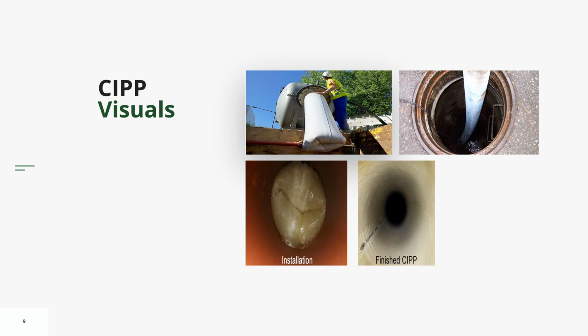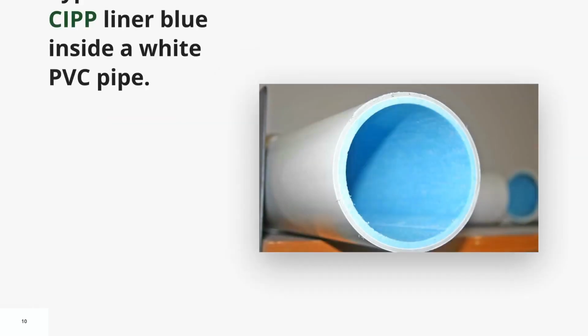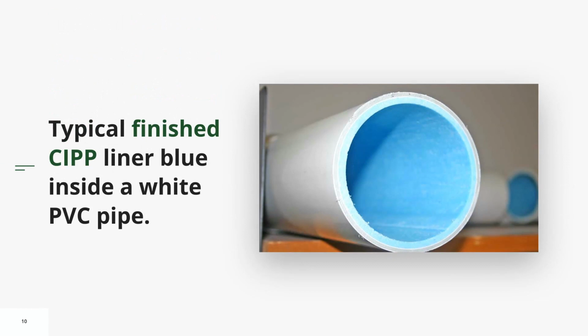Here is your typical finished product, just doing a cross-section through it. So the pipe on the outside of white is the existing PVC pipe, and then you've got your CIPP pipe on the inside. And again, you see that joint of the plastic on the right-hand side here at about 5 o'clock, that little white line going through there. That's the plastic on the inside again. So here's your typical resin or CIPP pipe and a CIPP pipe totally rehabilitated.